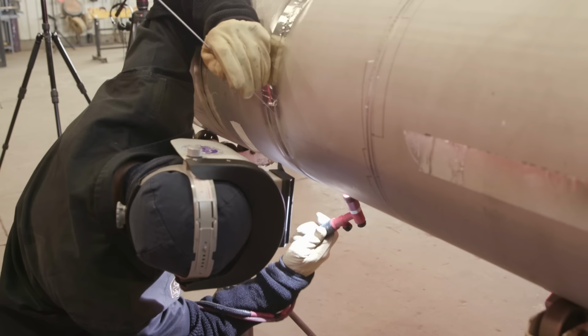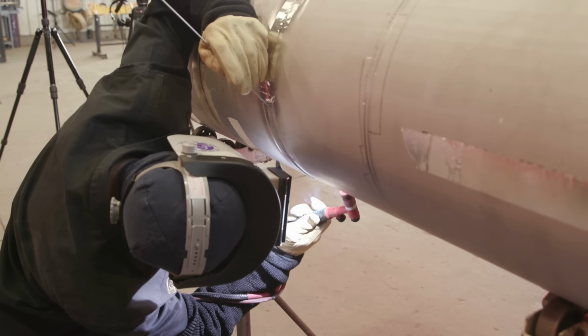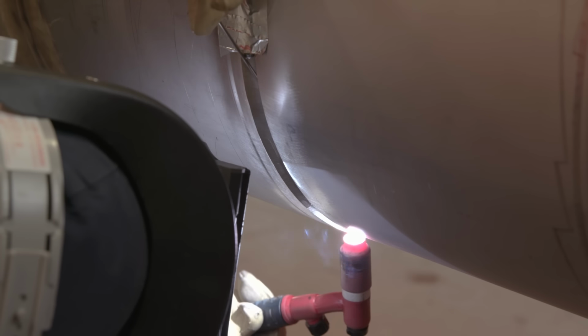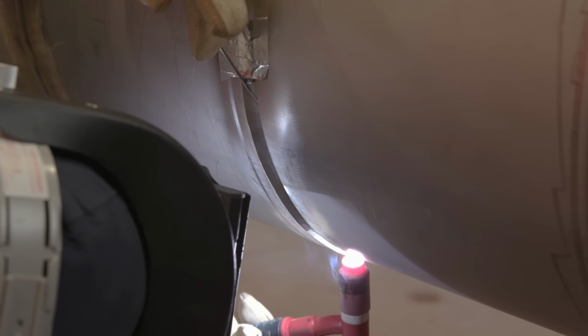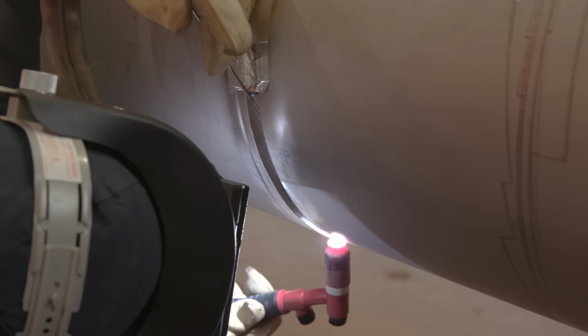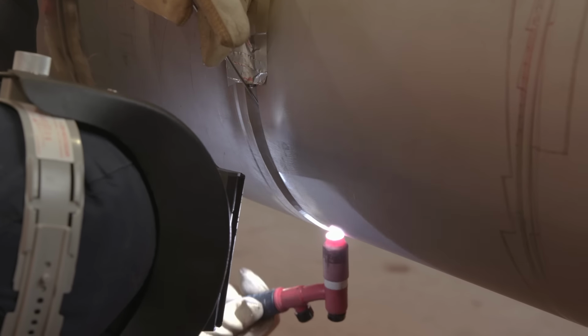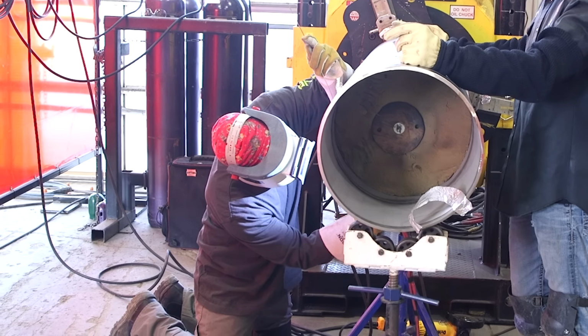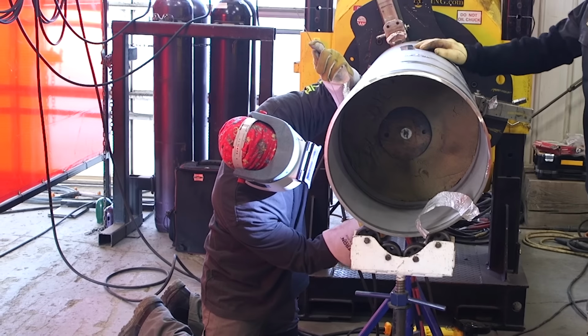I'm just soaking the puddle in there, and basically all the energy is being focused on the middle of the weld puddle, and the filler metal is being broken off. It's being melted into the weld puddle just by the energy of the torch there. If I heat up the leading edge, I'll end up opening keyholes, and when I bring the filler metal close, I'll prematurely melt the tip of the bevel off, or the tip of the filler metal off. But if I heat up the weld puddle, the energy of the weld puddle itself will be bringing down the tip of the filler metal.